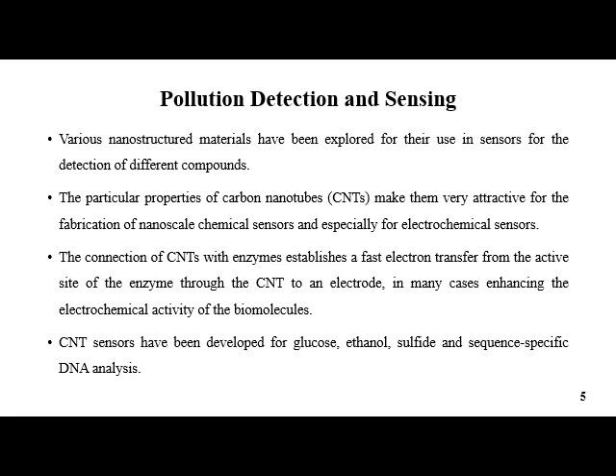The particular properties of carbon nanotubes (CNTs) make them very attractive for the fabrication of nanoscale chemical sensors, especially electrochemical sensors. Most sensors described so far use CNTs as a building block. Upon exposure to gases such as NO₂, NH₃, or O₃, the electrical resistance of CNTs changes dramatically, induced by charge transfer with the gas molecules or due to physical absorption.